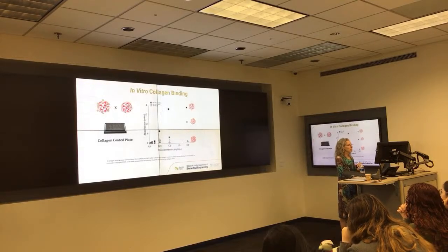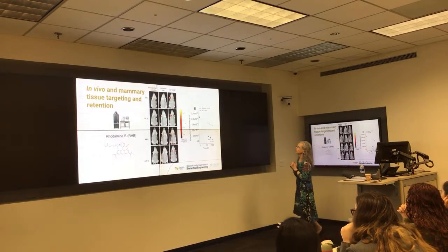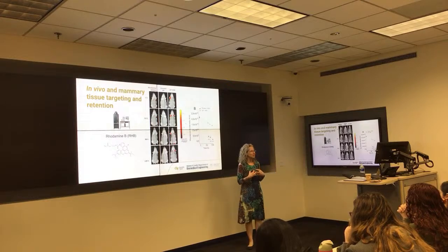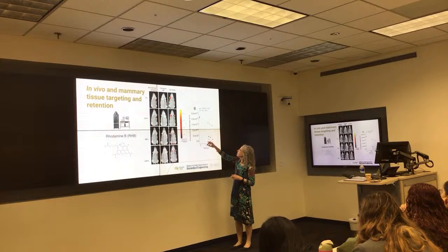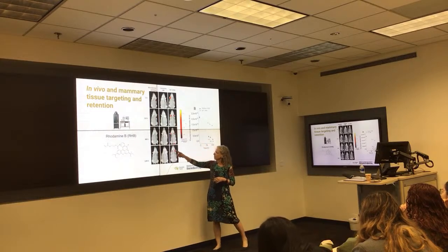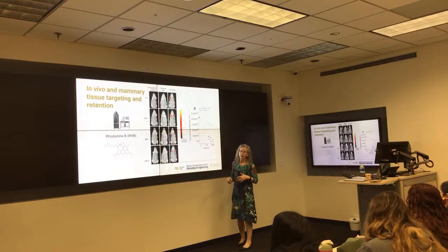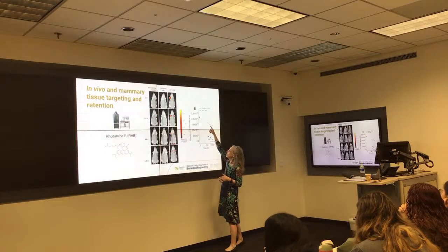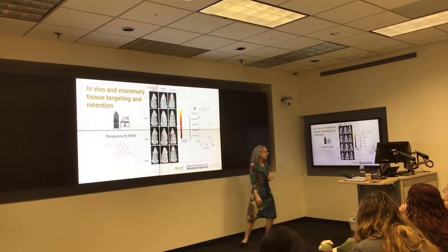These still collagen binding, I'm not going to go through that. She then went into animals and wanted to see if she injected the particles that bind to collagen, do they stay in the tissue for a long period of time? What she found was essentially that if she delivers particles that bind to collagen, they stay in the tissue over 100 hours. And if she delivers free drug, or just a free fluorophore, it comes out very quickly.